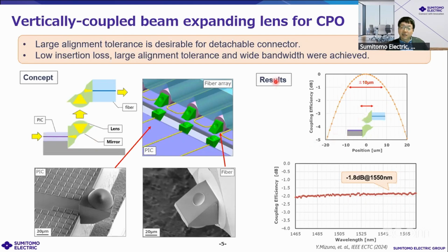The right side graph shows measurement results. The alignment tolerance is as large as 10 micrometers. And also the low insertion loss and flat wavelength characteristic is observed over 100 nanometer wavelength range. So this range will be very useful for detachable connection between PIC and fiber.